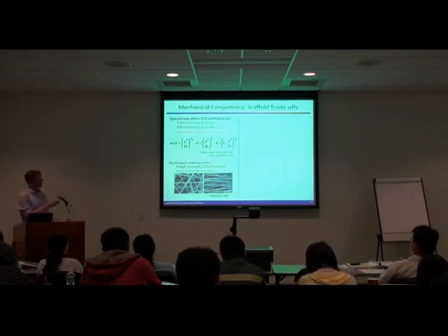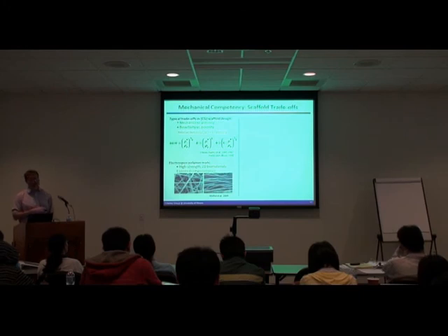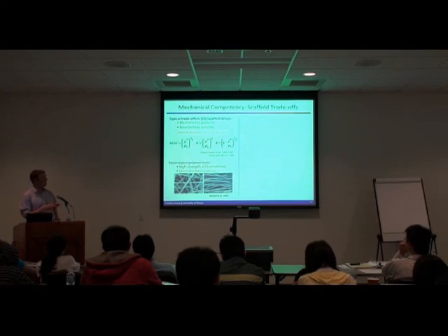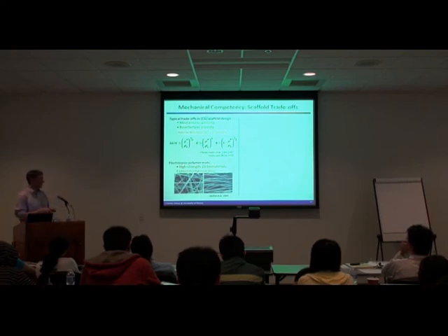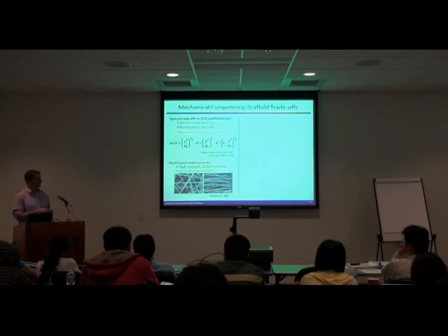However, if you start making the scaffold more and more dense in order to increase its strength, you reduce things such as permeability. So the cells aren't metabolically supported anymore and they start to die. So there's this complex relationship you need to understand. There have been a lot of groups working in orthopedic tissue engineering that have gone the route of electrospun polymer mats. Those work really well in the sense that these high density polymers, which can be either isotropic or highly anisotropic, are very high strength, but cells don't really penetrate into them. They're not a 3D structure, they're a 2D structure.